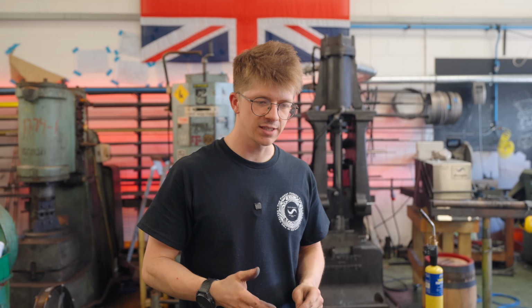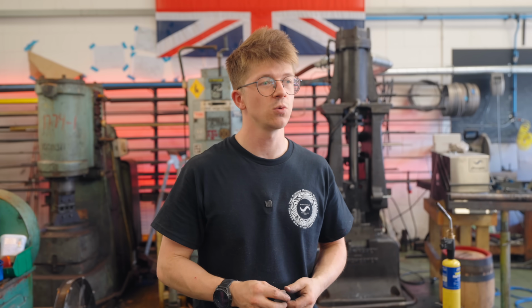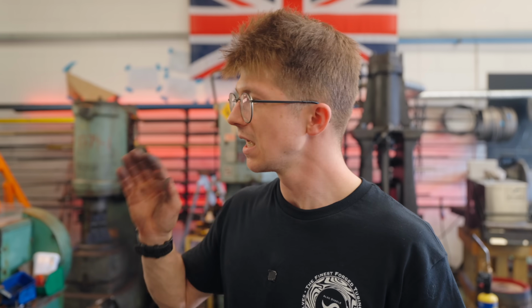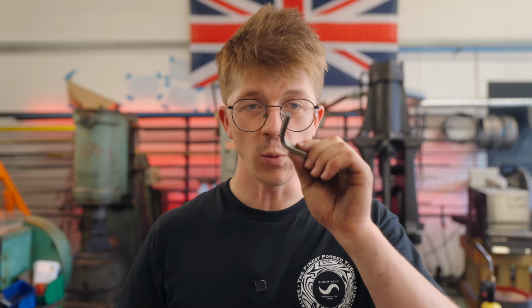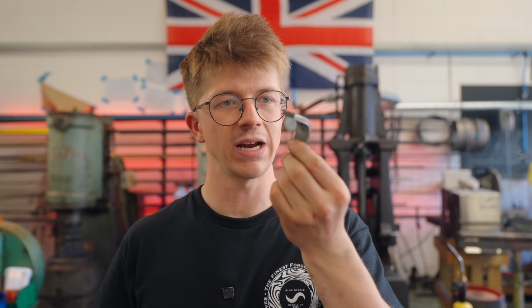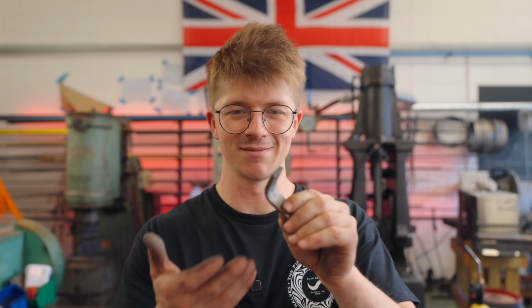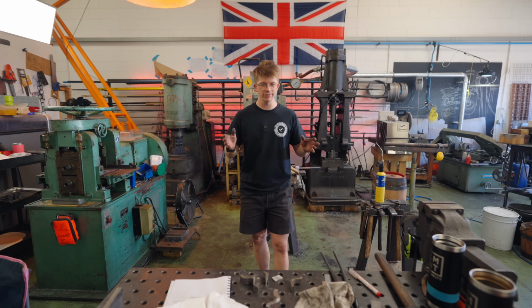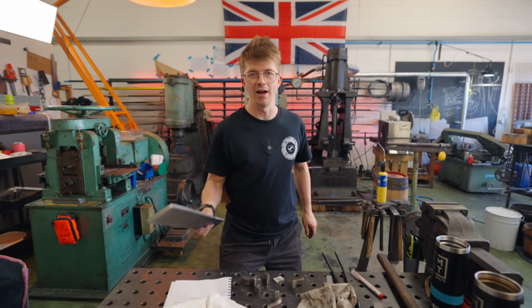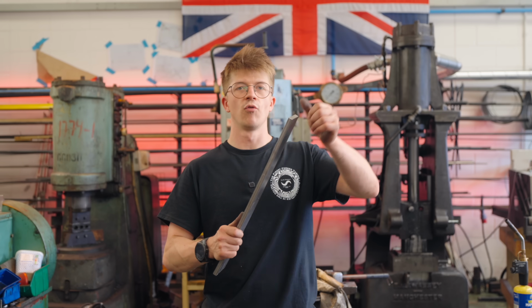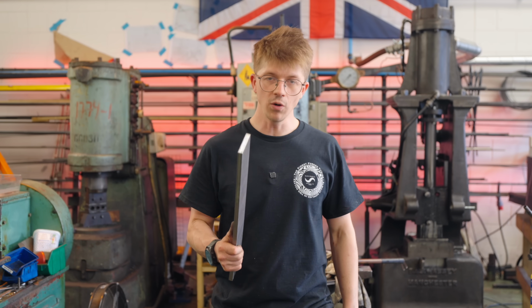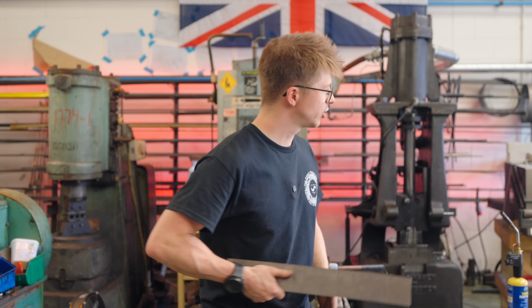And when I had the disasters earlier on in this video, I thought the answer was there is no chance of forging it. But at 850 degrees Celsius and 0.1 strain on each pass, we were able to forge it down and stretch it out and not have a significant loss of strength, because we can't even measure the loss of strength. It looks great. So that means I now have 2 roads ahead of me. I can either heat this up and then roll it down into some thinner bar, or heat this up and then just go straight to a quench. And I don't know what on earth I'm gonna do.